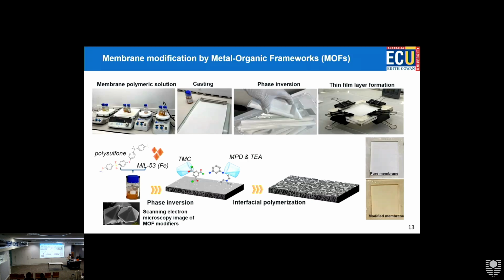What happens with this? We have two monomer solutions. One of them is in an organic phase, the other one is in an aqueous phase. So we do the aqueous phase soaking of the membrane, and then get rid of that solution, try to make the membrane dry. It goes into all pores, so we have it still there. And then we do the organic phase pouring on the surface, soaking on the surface. And then, because aqueous and organic phases, everyone knows, are immiscible, they cannot mix together, we have formation of the membrane only at the interface of those. So that layer that comes on the surface, which converts this to RO or forward osmosis with a high selectivity, is around 200 nanometers, which only occurs on the interface of those aqueous and organic phases, basically.